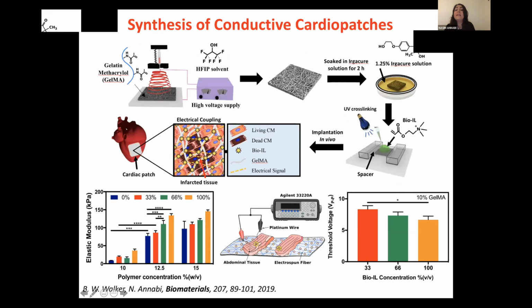To stabilize it, we soak it in a photoinitiator solution, and we add light to cross-link this fibrous structure, and then cross-link our acrylated bioionic liquid on the surface of this patch to functionalize it with bioionic liquid. Once we add BioIL, the patch was ready, so we can load it with different type of cells, or we can even use it as a scaffold without cells. We place it on the heart, we cross-link it with visible light to form this patch adhere to the surface of the heart.